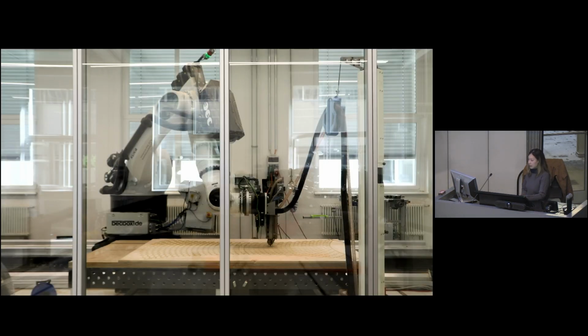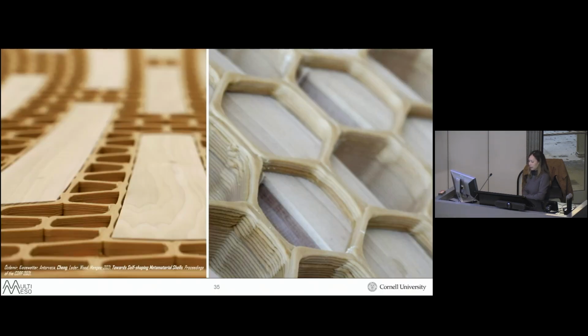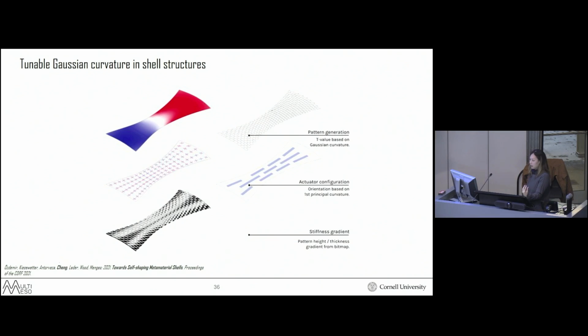And so based on this large-scale additive manufacturing platform that I developed, my master thesis students also explored this using the unique properties of auxetic metamaterials. And what's interesting is when you bend these metamaterial structures, it forms surfaces from positive to negative Gaussian curvatures depending on the pattern, from that hexagon to the inverted hexagon pattern. So they exploited this property of those auxetic patterns in self-forming bending active shell structures by modulating the pattern to control that variation in double curvature across the shell structure.